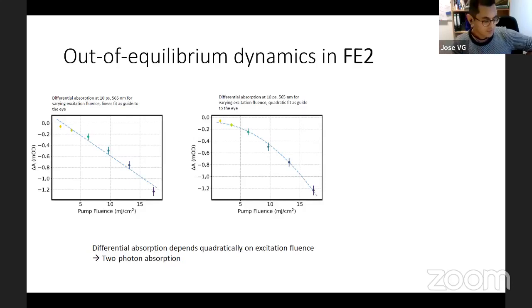One characteristic of this transition is observable by the differential absorption, or the change of the absorption with the pump fluence. In a normal absorption, the absorption with respect to the pump fluence is linear, but in a 2-photon absorption, it's quadratic. And we can observe this quadratic behavior when we photoexcite at 780 nanometers.